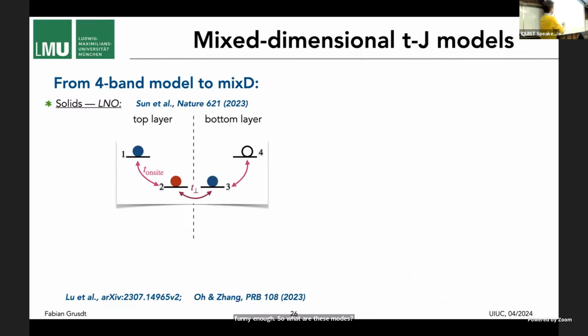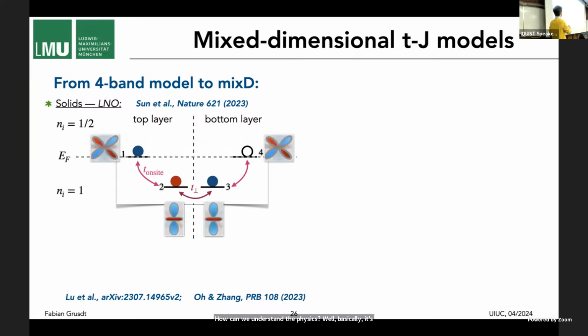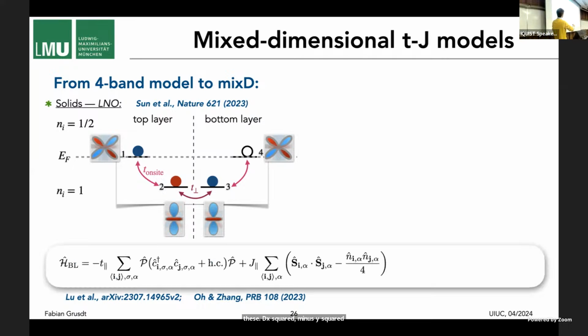Well, basically, it's a bilayer model, a top layer, bottom layer. Both of them have two relevant orbitals. And there are lower lying d_z² orbitals down here. They're occupied by a single fermion. There's again a large Hubbard interaction that prevents more from being occupied. And the physics, we think, more or less takes place in these d_x²−y² orbitals. Those are exactly the orbitals that also play a role in the square lattice Hubbard type physics, right? And all the square lattice Hubbard physics goes into the plane, right? So you have one Hubbard type plane here and one Hubbard type plane here.